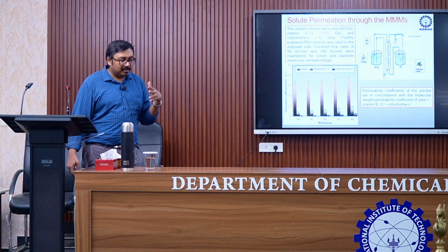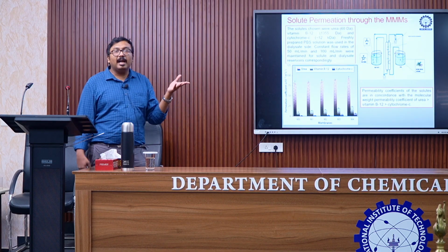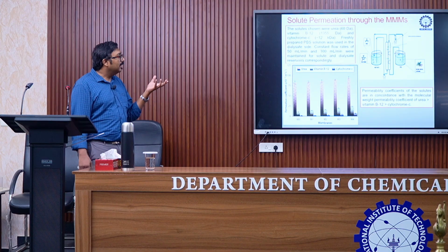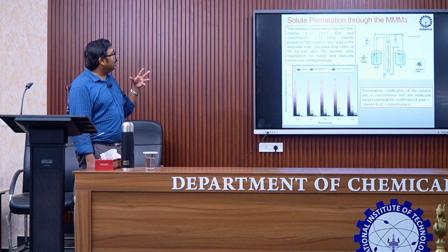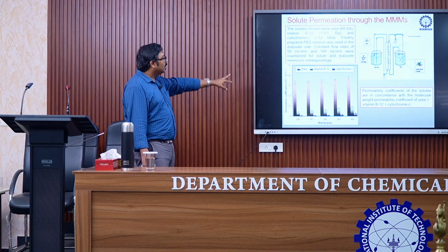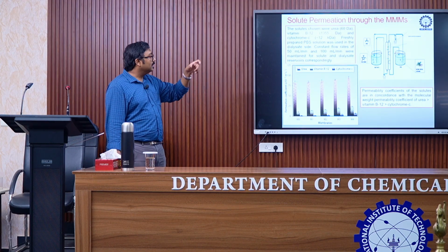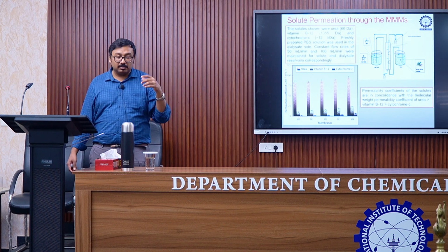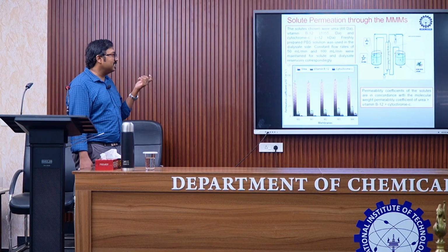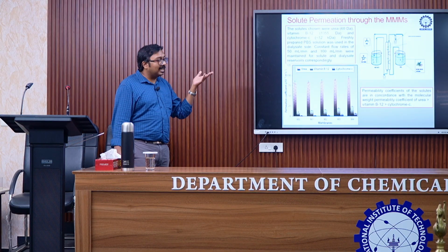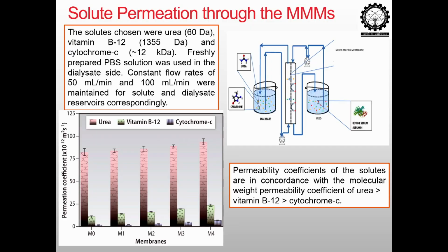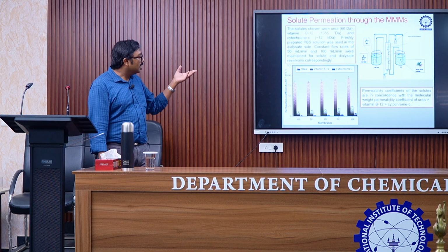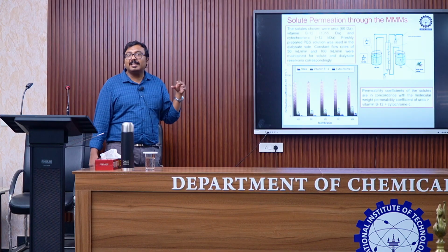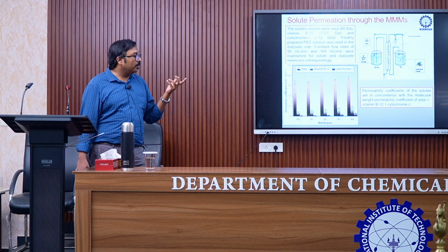So finally, we had tested the membranes for the biocompatibility, and once we found that they were biocompatible, we have done an in vitro study for removing solutes. So the three solutes chosen were all from different size ranges. So you have urea. Urea is around 60 Dalton, very small. Vitamin B12 is around 1000 Dalton, and cytochrome C. Cytochrome C doesn't exist in the body, but it was used as a surrogate molecule. So surrogate meaning instead of lysozyme which has around 11,800 Dalton, because cytochrome C has a color and it's around 12,000 Dalton and it can be easily visualized with any kind of spectroscopy. So that is why we used it.